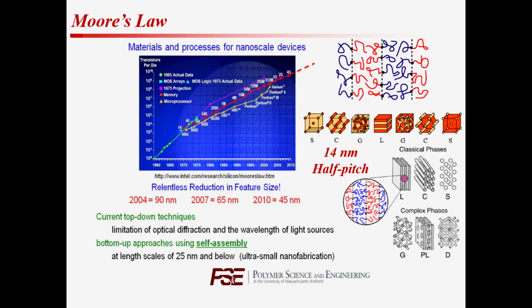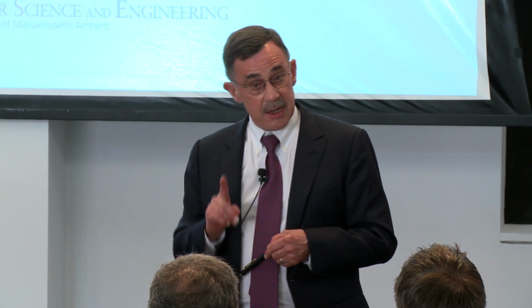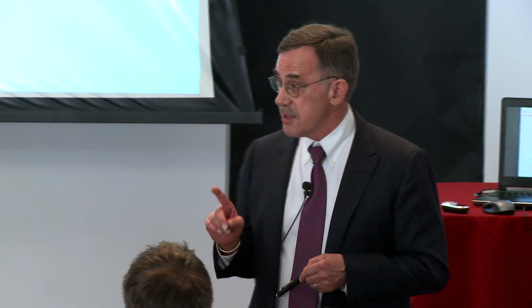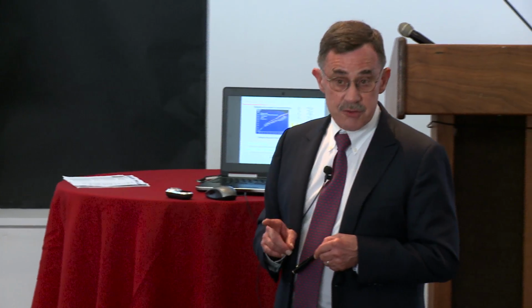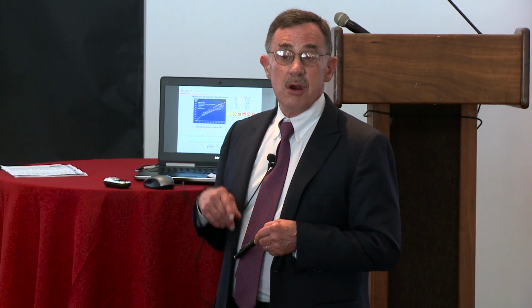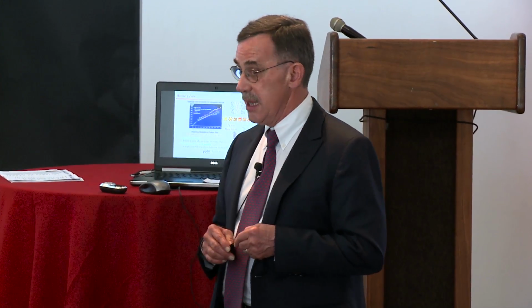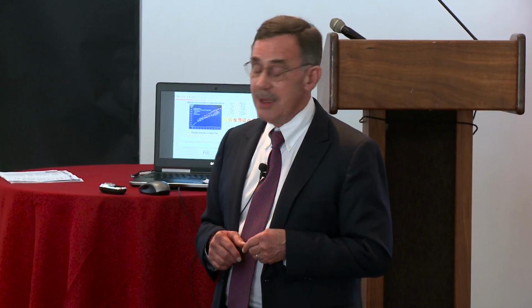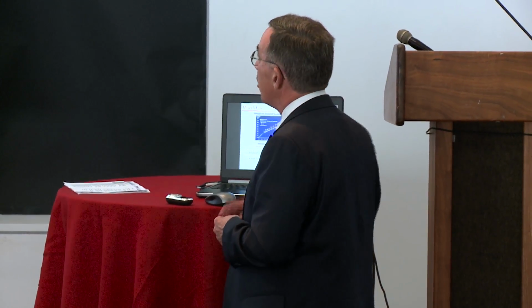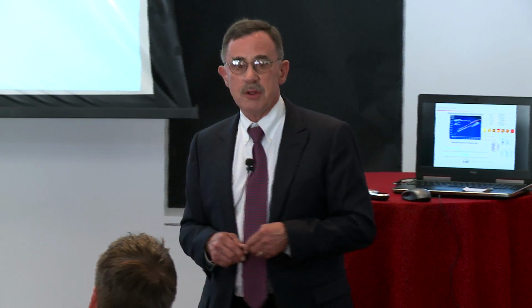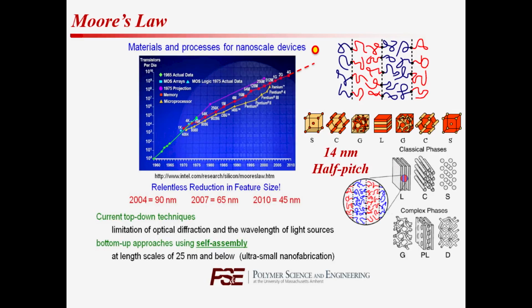However, if I can take these molecules and make them in thin films, and if I can control the orientation of the molecules, and if I can control the lateral ordering of these molecules, there are some very unique applications that will emerge. And in fact, if I can learn to control the size scale of the structures, and get structures where I would have a full pitch of 4 or 2 nanometers, it's awfully small, then I would place myself orders of magnitude above Moore's law. And I think we can do that very easily, and we're close to being able to do that now.